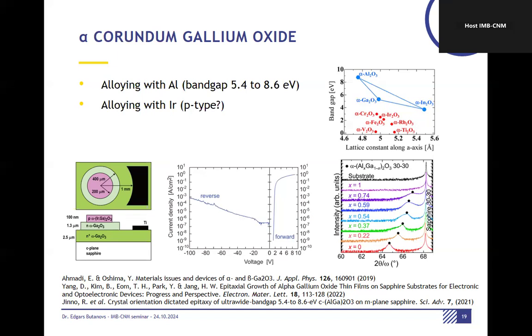However, aluminum oxide is corundum, so it's the same crystalline structure. The lattice mismatch is not that big, so there are some demonstrations. By growing it in alpha phase, you can alloy it basically up to 8.6 eV. There's some demonstration, I think, from the Cornell Group in the US on this, as well as some interesting results of alloying with iridium. There are very few papers on that. That's from, I think, Kaneko Group in Japan.